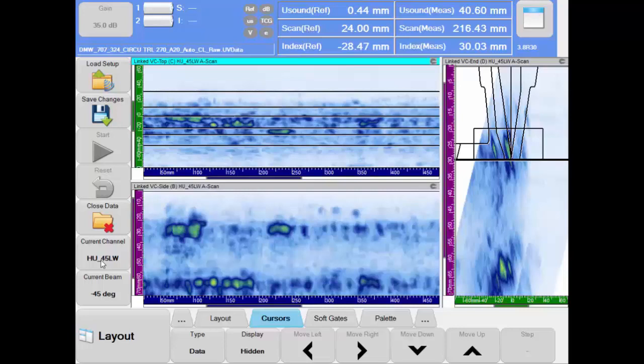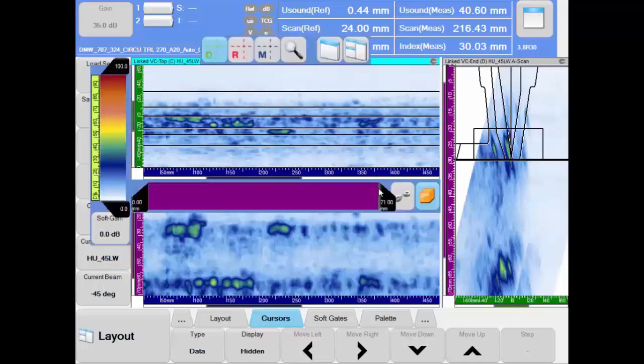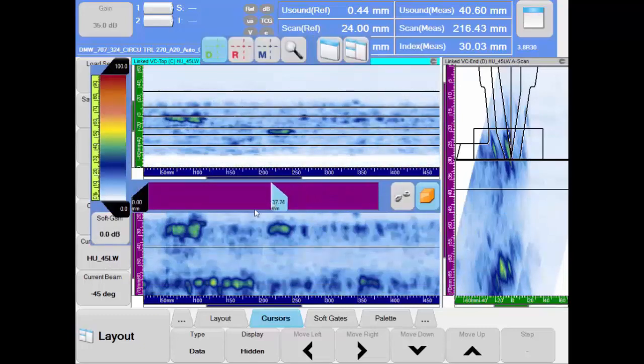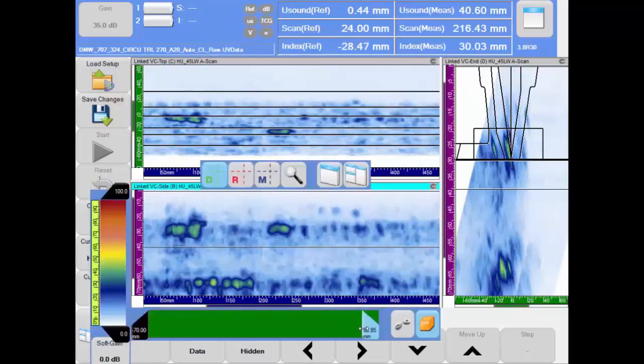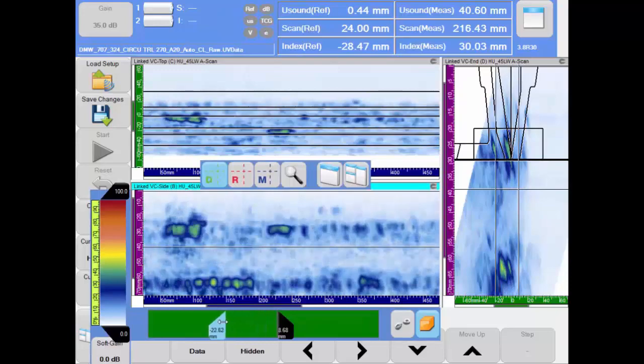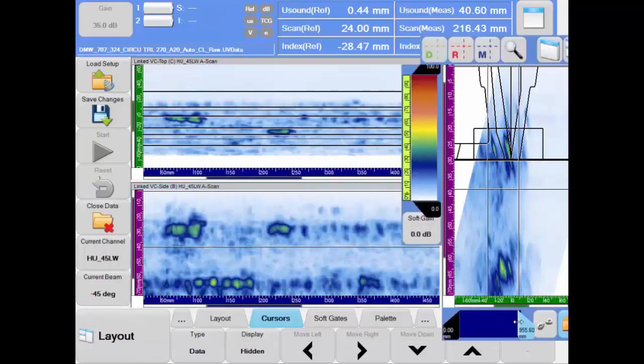We are looking at the previously merged data group from the 45-degree L-wave linear scan on a 12-inch diameter dissimilar metal weld with several acoustic interfaces and a wall thickness of 30 millimeters. The screen layout is similar to the one we used before in this webinar. After using the projection gates to eliminate mode-converted echoes, we can clearly observe two indications near the ID of the weld. They are signals from two circumferential ID surface breaking cracks.